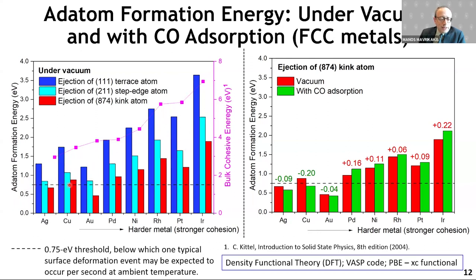The last thing I want to point out here is this 3/4 of an electron volt dashed line, which we deliberately drew to emphasize that a process, an Arrhenius type of process, a rate process, that has a barrier of 0.75 electron volts, you will have at room temperature one event per second. So if you are below this, as you are on silver and gold, for instance, then you have one metal atom ejection per second from the kink site, even under vacuum. So it's a dynamic process, yet an ergodic process, okay?